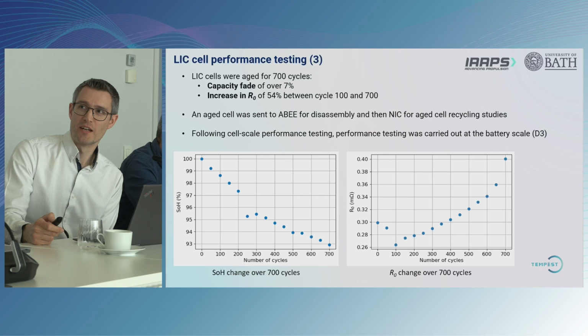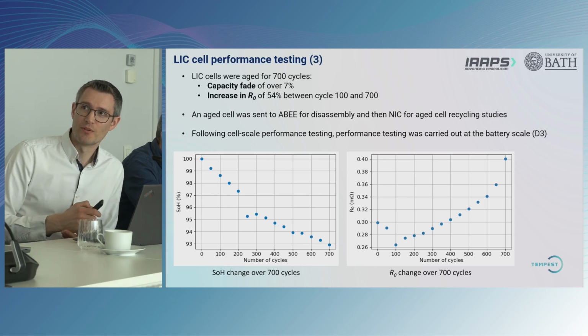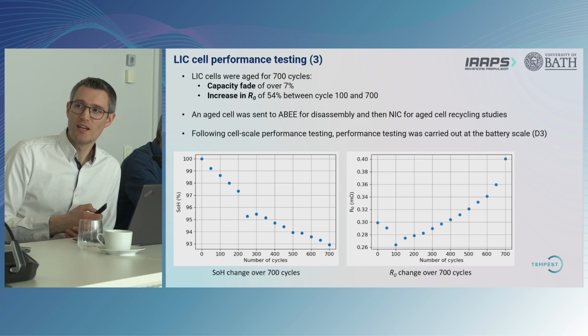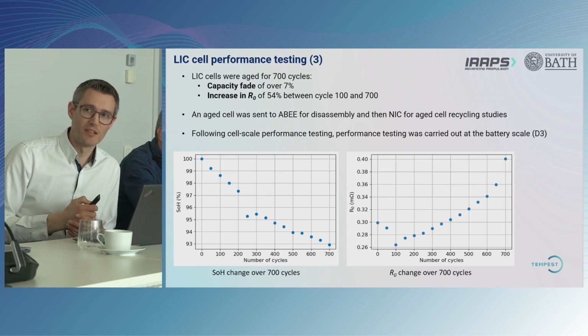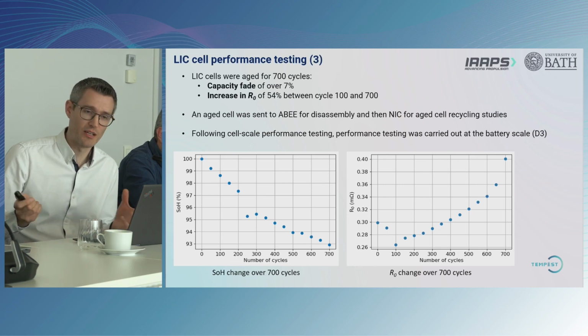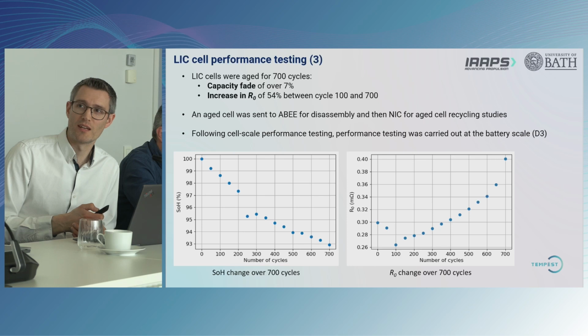We also did some degradation tests. So we did some capacity degradation checks over 700 cycles, and this was to examine how the cell performs over the long term. So this demonstrator with the lithium-ion cells, demonstrator number 3, was specifically targeted for stationary storage applications. That was the target application of this kind of technology, and all the technology that was going into it was with that in mind. And so we were doing these cycles with a view to examining how it would perform in that kind of application.